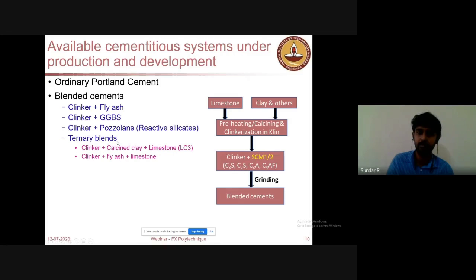These three are binary blends, and this is the ternary blend, which has 2 SCMs. So after the regular cement manufacture process, 1 or 2 SCMs will be added to the clinker, and then it will be ground to form the blended cement. So this is how blended cements are made.